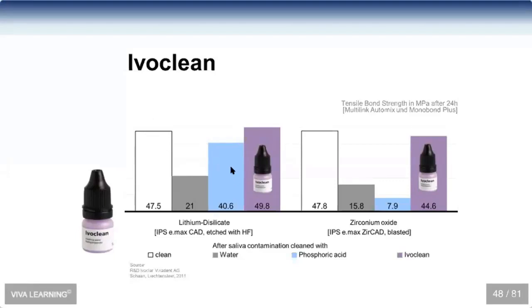Now, interestingly, this is phosphoric acid, this little blue bar that you see right here. So phosphoric acid, not hydrofluoric. Hydrofluoric is what the lab used to etch the inside. Phosphoric is what we use to etch enamel. Phosphoric acid does work pretty well on the inside of Emax lithium disilicate. And so you could clean the inside of the crown like that, which is what we've been taught to do for the last 20 years with all ceramic materials, going back to Empress and the days before that. But the highest bond strength that you get is by using the IvoClean, but phosphoric acid is a close second.